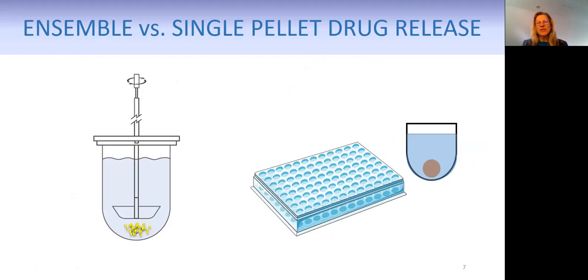However, if you want to interpret drug release mechanisms, especially with these small multiparticulate units, you have to investigate not only the ensemble of drug release, where you have hundreds of pellets mixed together in the USP paddle apparatus. The dissolution profile you're observing is the sum of the individual drug release of each single pellet. So we also did some single pellet drug release studies where we exposed the pellets to 400 microliters of medium in small well plates.